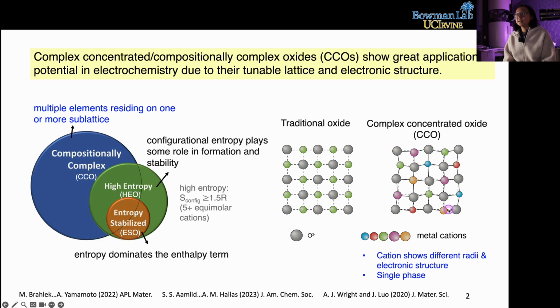So you can see in this schematic, the CCOs also include the high-entropy oxide and the entropy-stabilized oxide, depending on how much the configurational entropy plays a role in the phase stability of the materials. In the CCOs, we can see they have multiple cations, and each cation shows different radii and electronic structures. But all the CCOs still stay in a single phase.